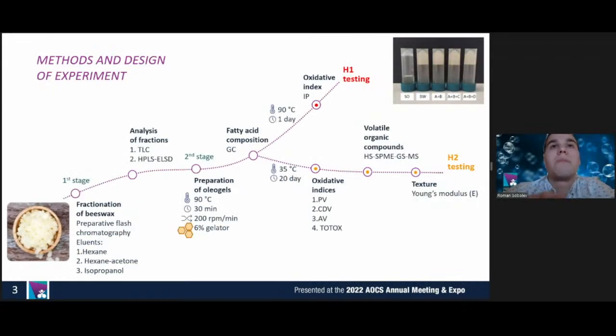Generally, the study can be divided into two stages. The first stage includes the fractionation of beeswax and identification of the component composition. The second stage includes the preparation and analysis of oleogels in sunflower oil. A fatty acid composition analysis was performed for all samples. Next, to test the first hypothesis, the induction period of the samples was determined at a temperature above the melting point, at 90 degrees Celsius.